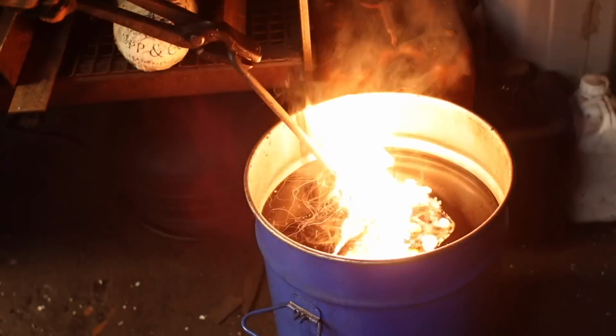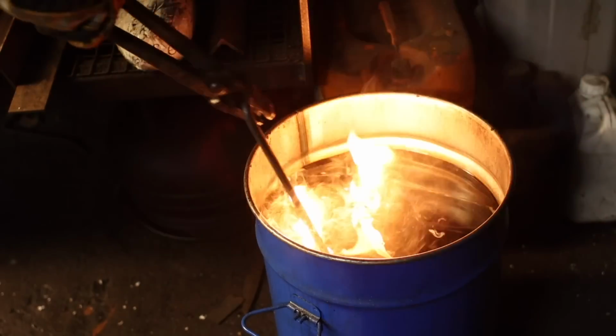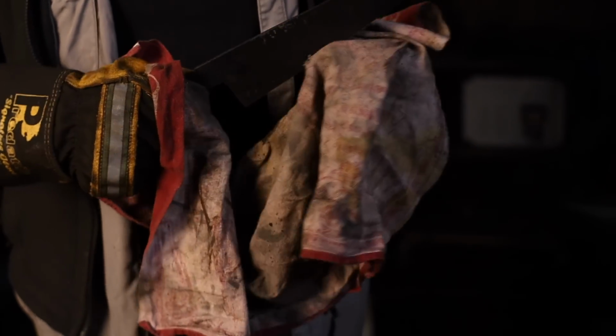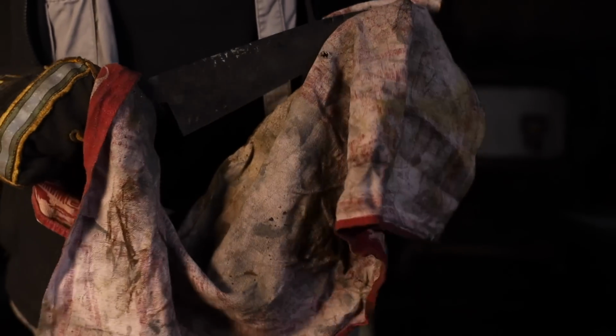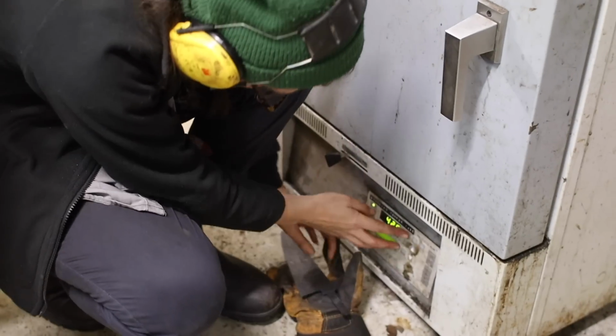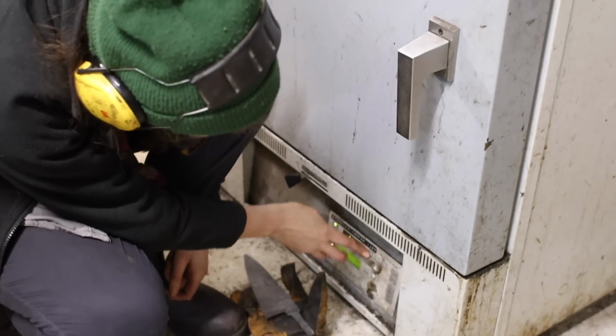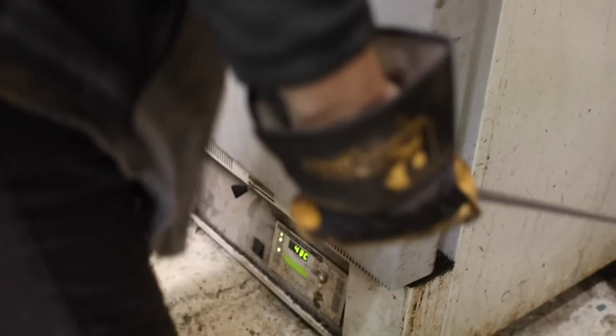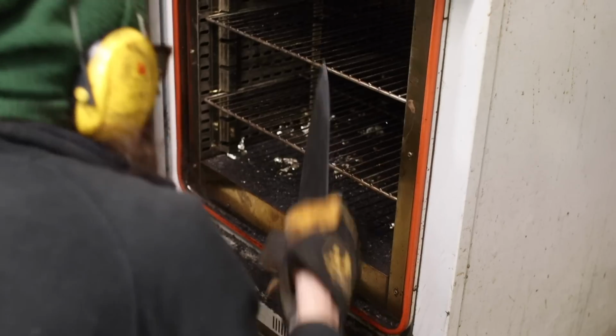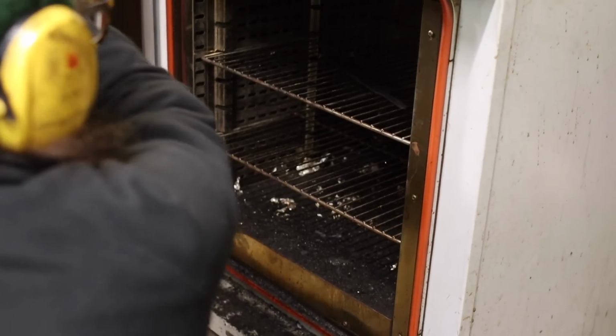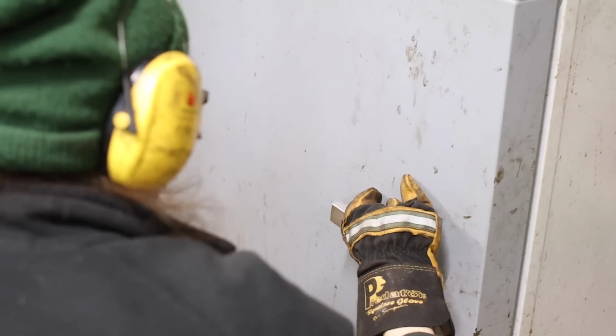Holly heats a barrel of oil to about 70 degrees, which is going to be our cooling off fluid. By plunging the 800 degree blade into the cooler oil, she will change the grain structure of the steel, hardening it and making it capable of retaining its sharp edge. This can also make it pretty brittle, so if we did drop it at this stage, God forbid, it would shatter like glass. No pressure, Holly. To reduce its brittleness, the blade is finally tempered in an oven at 200 degrees for 2 hours. This again changes the structure of the steel, producing a good balance between hardness, toughness, and corrosion resistance for the finished knife blade.